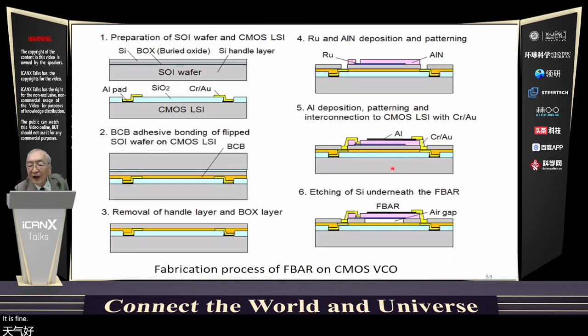Fabrication process of the FBAR on CMOS LSI is shown in this slide. Silicon on insulator SOI wafer, which is flipped upside down, is bonded on the CMOS LSI wafer using adhesive polymer BCB in two. After the handle wafer and buried oxide layer of the SOI wafer are removed, ruthenium and aluminum nitride are deposited and patterned in four. Aluminum top electrode and interconnection to the CMOS LSI are formed, and finally, silicon layer under the FBAR is etched out.